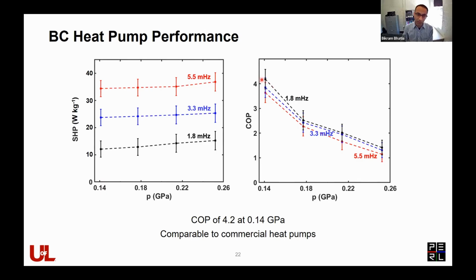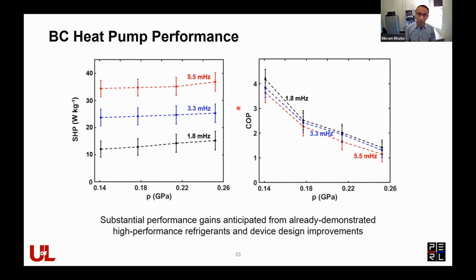But at the lowest pressure setting that we tested, we actually measured a COP of around 4.2 with this commercially available material, which, if you compare with a commercial heat pump, the typical COP is around 3 to 4. So even with this first prototype, we were able to report COPs that are competitive with commercial heat pumps. And we are really excited because this is just a first prototype. There's obviously a lot of device optimization that could improve the performance, and we are working on some of that.